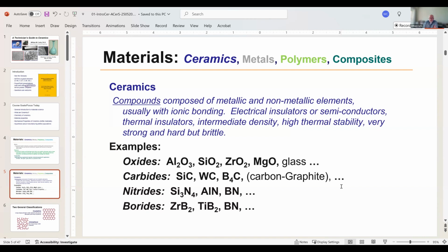So at the bottom, you see examples. We have oxides, which are by far the most common. Okay, so oxides, anything we do with this, includes glass, by the way. Aluminum oxide is probably the most common oxide that you're aware of. Silica, for example, SiO2, can be crystalline as in quartz, or it can be amorphous as a glass. Zirconia is famous. If we add a little bit of yttria to this, we get a partially stabilized zirconia, which resists crack propagation. So we have then accomplished toughness or less brittle behavior. So oxides comprise probably the vast majority of the manufactured ceramics today, but that is likely changing with time.